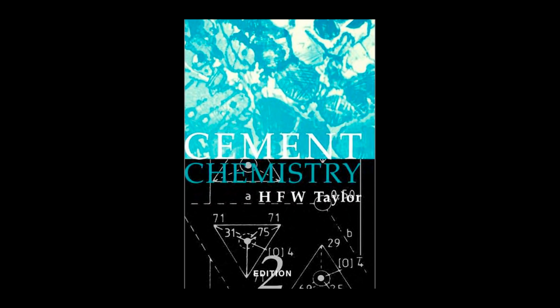So durability engineering is essentially a race to disconnect those capillary pores. That's it exactly. You want the system to reach a critical threshold where those larger connected capillaries are broken up, forcing any penetrating agent to travel through the much slower, more tortuous gel pores. Right. And do we know where that threshold is? Yeah, we do. Modeling calculations show us these critical thresholds.